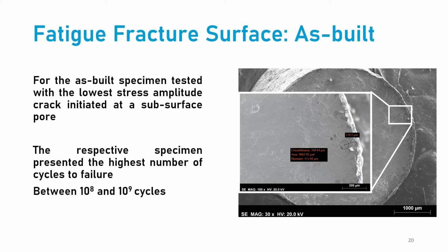Now, only the lowest stress amplitude specimens for as-built specimens showed a crack initiation at the subsurface. This also resulted in the specimen with the highest life and the highest number of cycles to failure.